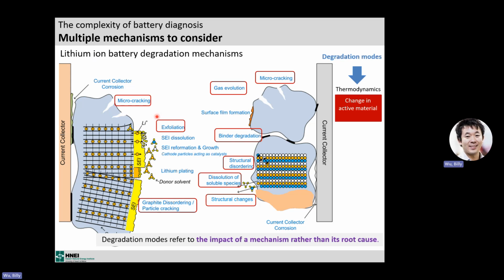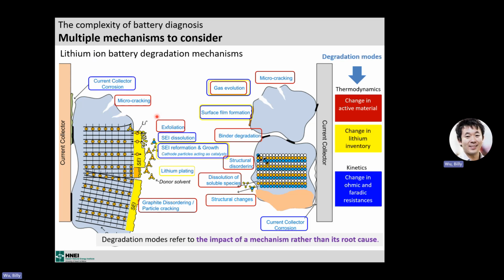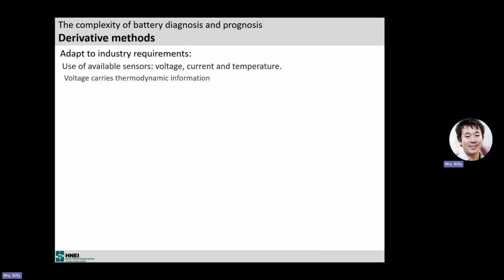So we can classify those degradations in terms of amount of active material, change of lithium inventory, and change of kinetics. Three big families of degradation modes. Because no matter what happened to your cell, you can always decompose that degradation into how much material was lost, how much lithium was lost, and how much the kinetics were affected. If you take the example of the SEI growth, it is going to consume lithium, so you have a loss of lithium inventory. After a while, the resistance is going to increase too. That's the kinetics. And if you clog some pores, you're going to lose material. So you see, I could decompose any of those degradations into some of the degradation modes. So that's half of the battle, right? We simplified the problem from 20 plus mechanisms to 3 families.